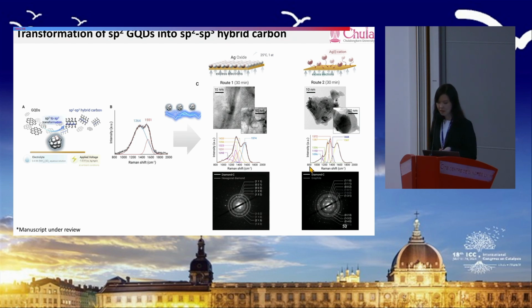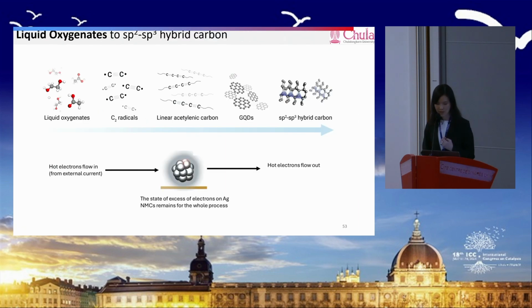And here is the Raman of the graphene quantum dots. It did change a lot. So it's possible that there is a transformation. Actually, I would tell you that it depends on the size of the graphene quantum dots, and there are still many parameters here, but we see some possibility to manipulate the sp2, sp3 hybridization of the carbon under this nanoscale system.